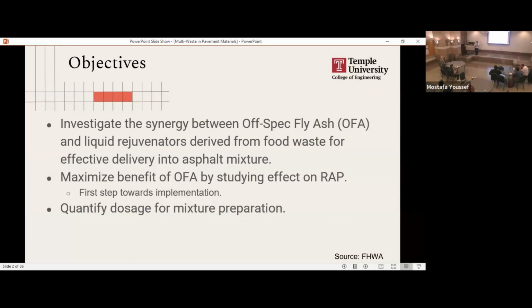Through some chemical extraction, we managed to get some bio oil of certain characteristics that have some rejuvenating effect on asphalt. So the idea here was blending the waste ash and the oil extracted from the waste food together to create this additive that could replace part of the asphalt and in addition enhance its properties at the same time. But these rejuvenating effects of the oil allow us to use recycled asphalt as well and rejuvenate its properties.